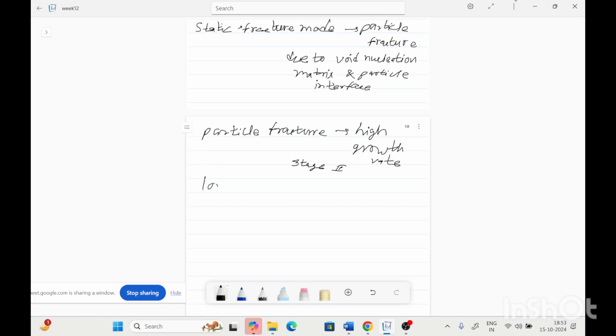And for the lower crack growth rates, the crack bridging is generally observed. Means for the higher growth rate in the mid range, the particle fracture, and in the lower crack growth rate, the crack bridging due to particle fracture.